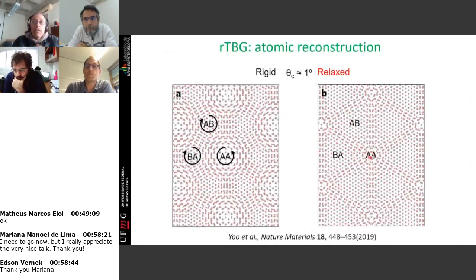They're stuck here, okay? These high density of states are stuck at this location because the material is different here, the material is different there. Okay. And the phonons, are they localized around the regions where you have a strong gradient of strain, or is there no relation to that?